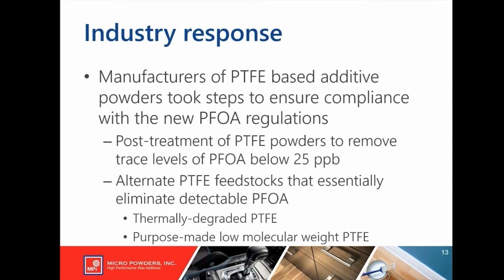So what was the industry's response? Anyone who was making a PTFE-based material had to figure out how they were going to comply with this new regulation. One approach was to take existing products that were manufactured and use some sort of post-treatment processing to make sure that trace levels of PFOA were below that 25 ppb limit. Another approach was to use alternate feedstocks before they are micronized and size reduced that essentially eliminate detectable PFOA. So rather than using electron beam to break down the polymer, you can use thermally degraded PTFE, which typically generates not detectable levels of PFOA. So that was one approach to take, is to move from electron beam irradiation to thermally degraded PTFE.